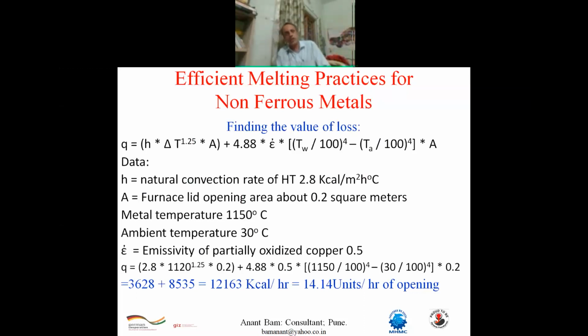First the material is charged, it takes about 5 to 7 minutes to go to the bottom and turn to liquid. Then the next charge is put into the crucible. In between these two charges, one can keep the crucible closed, covered. So as such, we can save on this 40% of the time.